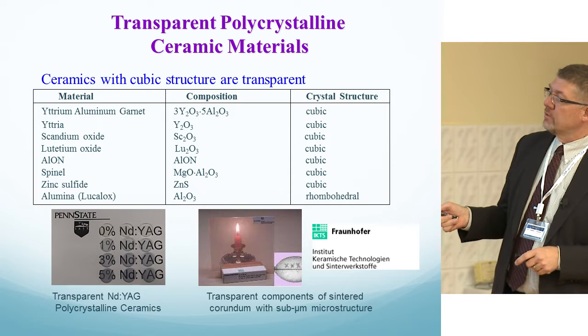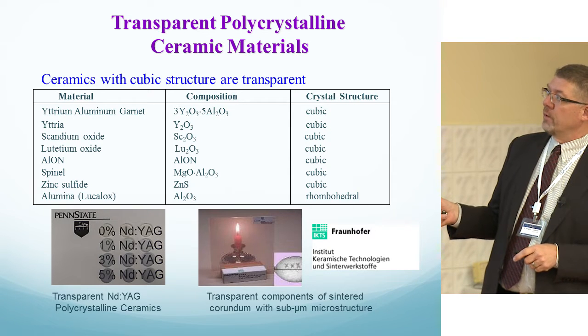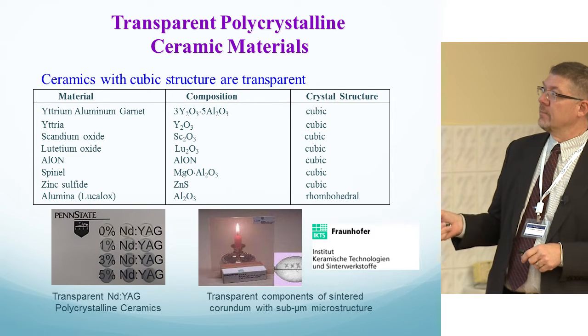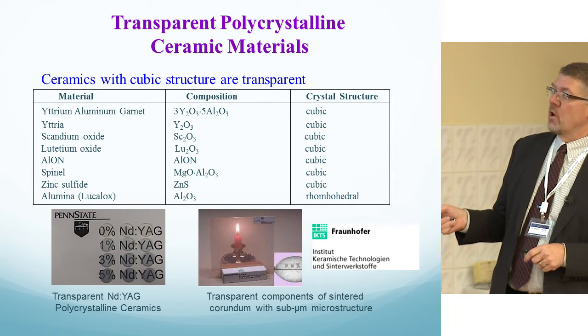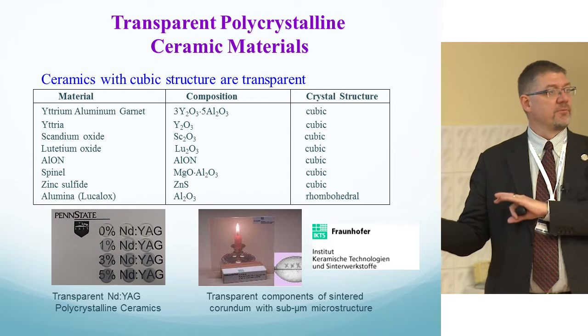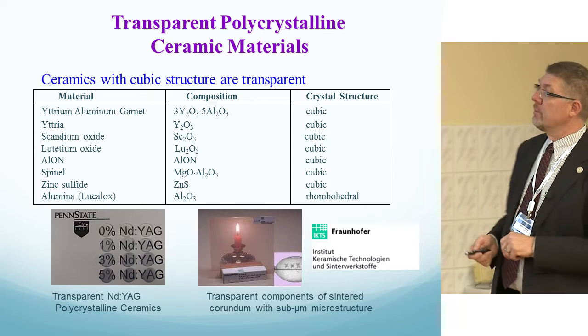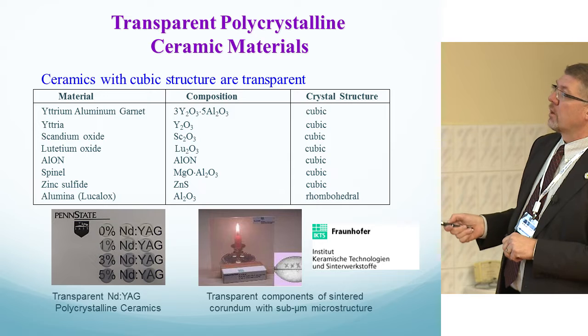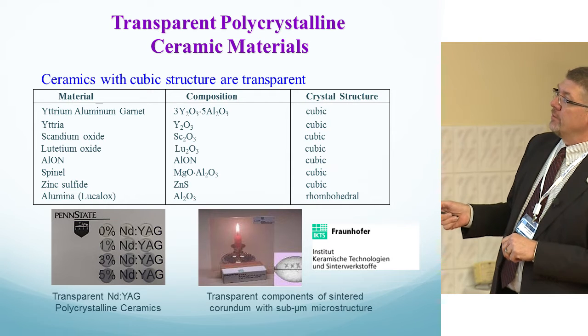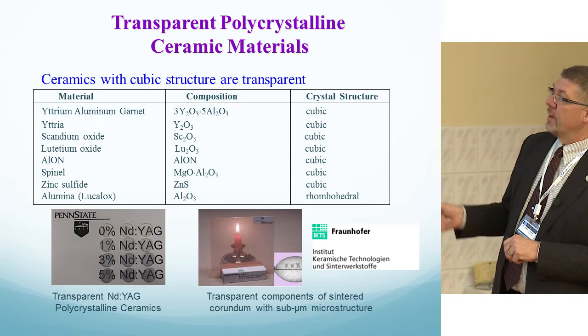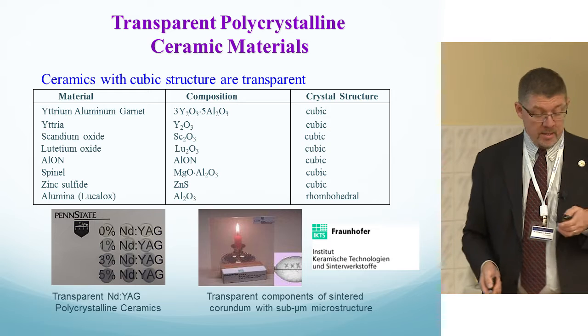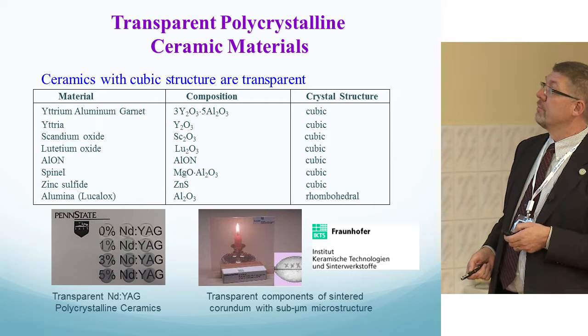Some of the work you see here is from our partnering with Penn State, where they grew a series of undoped, 1%, 3%, 5% neodymium samples. The darkness is not transparency of the material, it's actually the absorption of the neodymium. And here's a corundum, which is the aluminum oxide you see here. So that's the level of transparency of the material that was first being developed at Fraunhofer's group.